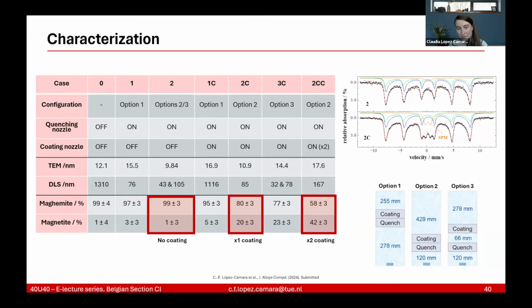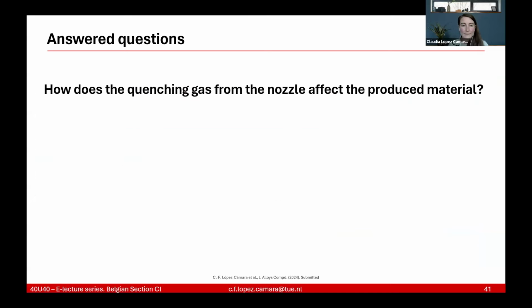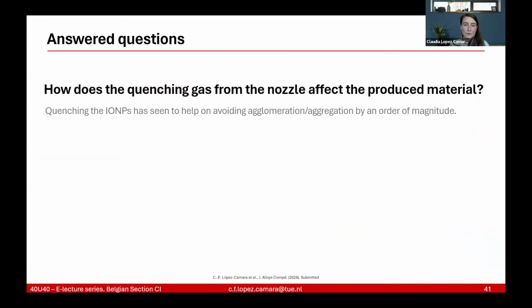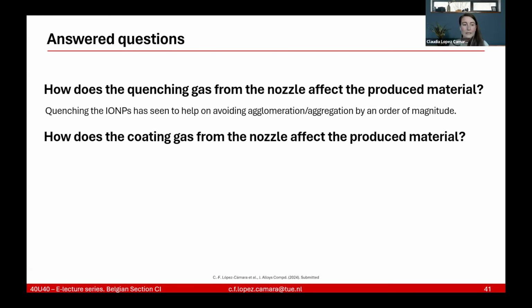That was actually not that trivial. And therefore, we get the answer solution. So how does the quenching gas from the nozzle affect the produced material? Generally, we saw that the quenching of the iron oxide nanoparticles seemed to help on avoiding agglomeration and aggregation, even by an order of magnitude.